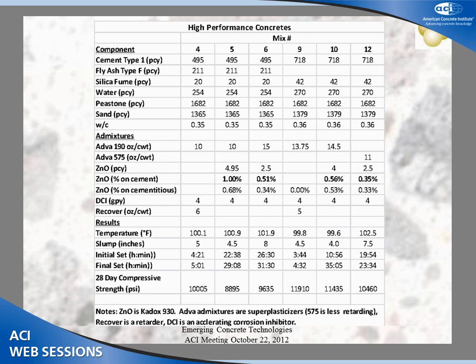In the case of higher performance mixes, produced at about a 0.35 to 0.36 water to cement ratio, basically we saw the same type of trend, very long setting times associated with the use of the zinc oxide. And as you can see here, if you look towards the bottom again, these series of concrete mixes were run at relatively high temperature concretes. We're looking at about 100-degree Fahrenheit concrete. So in spite of the high temperature of the mix, we still saw relatively high times to initial and final set. But it does demonstrate, too, that you can make hot concrete as long as you control the hydration reaction. You can still get glorious strength out of it.